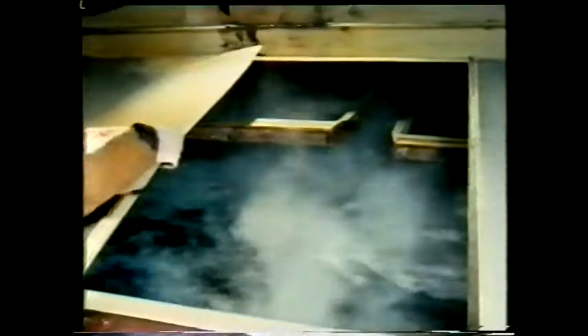Before galvanising, the steel railings must be thoroughly cleaned. This is done by pickling the steel in a bath of hot sulphuric acid. The railings travel through the bath and in the process all the rust is removed. The railings are left in the acid for about 20 minutes, then rinsed in hot water.